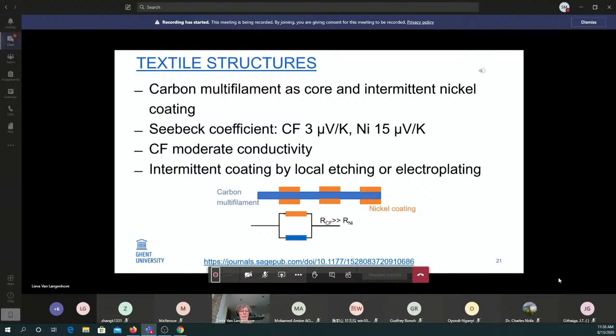The coating can be achieved either by local etching of a nickel coating on a nickel carbon fiber material, which can be just bought commercially via the internet, or by local electroplating of the nickel onto the carbon fiber multifilament.